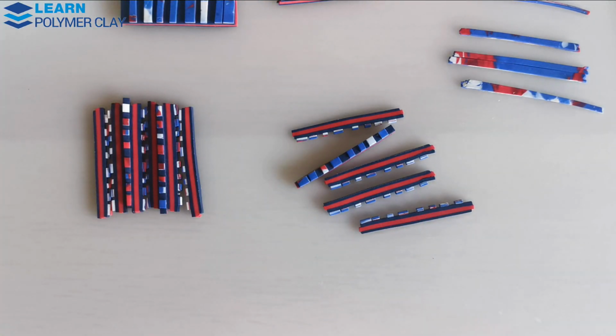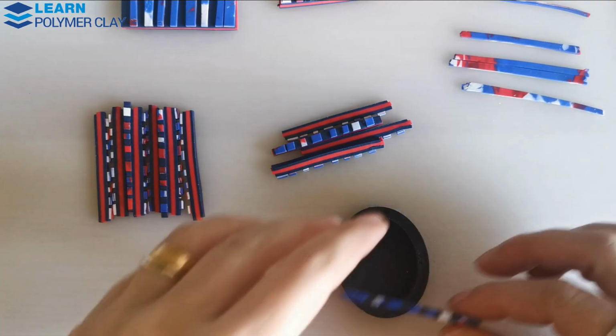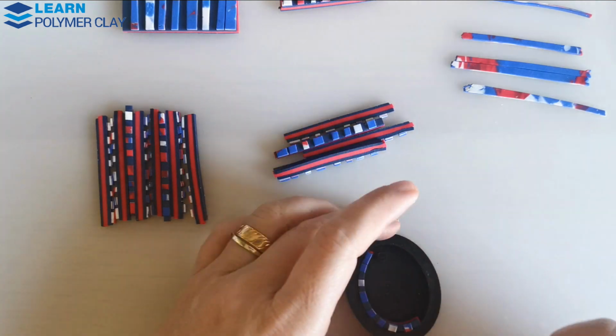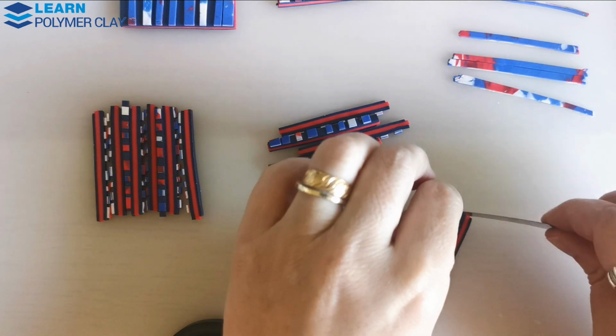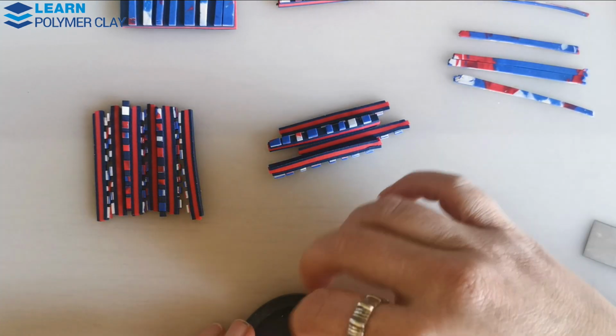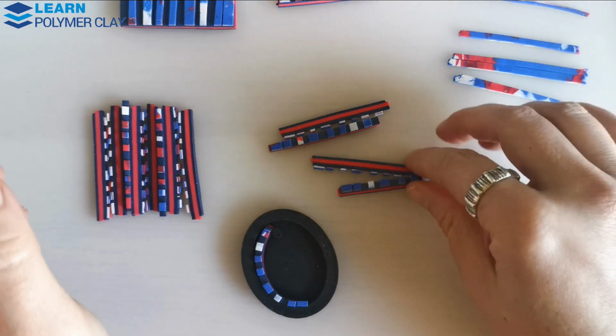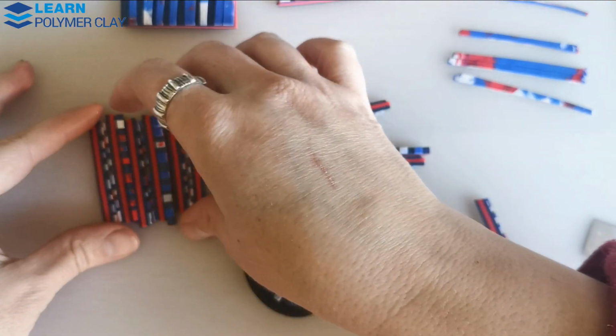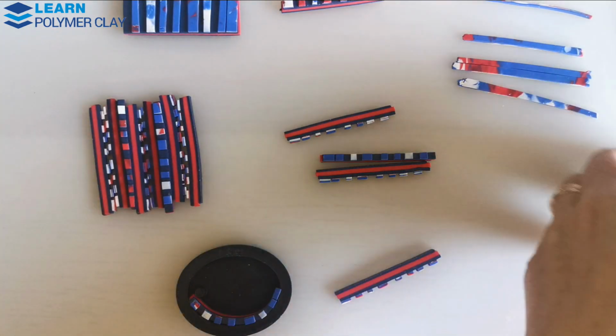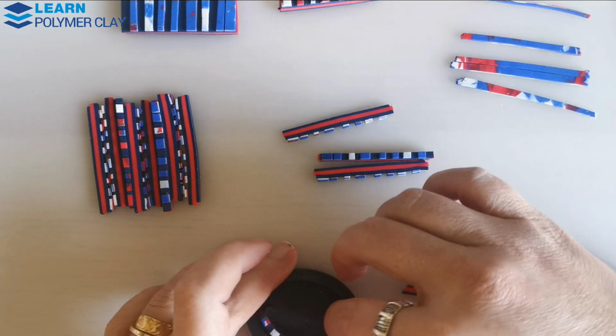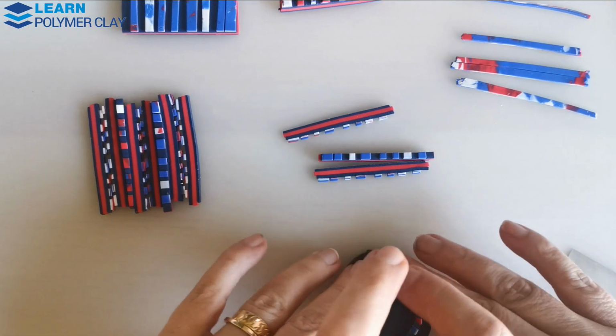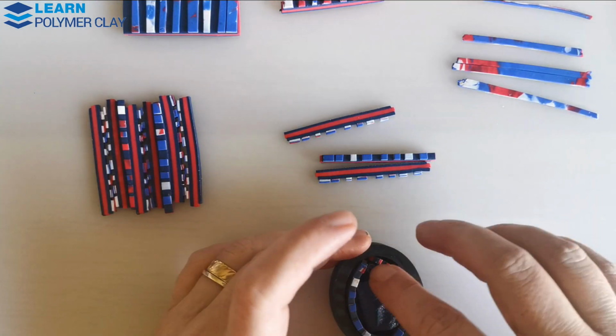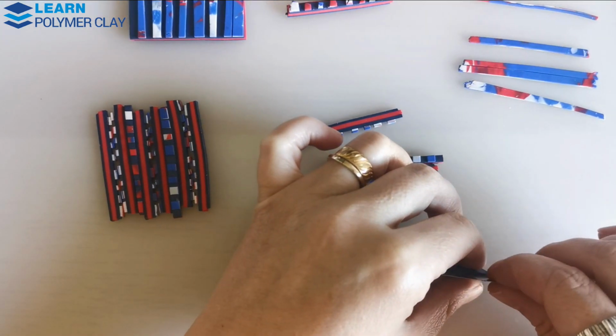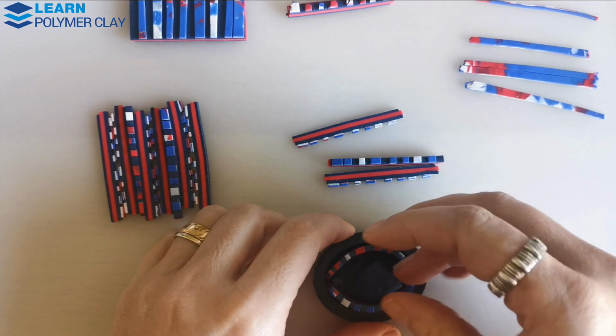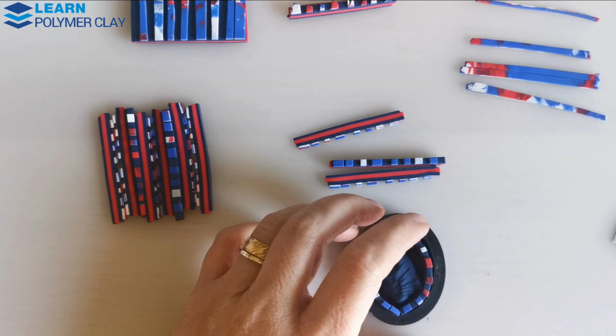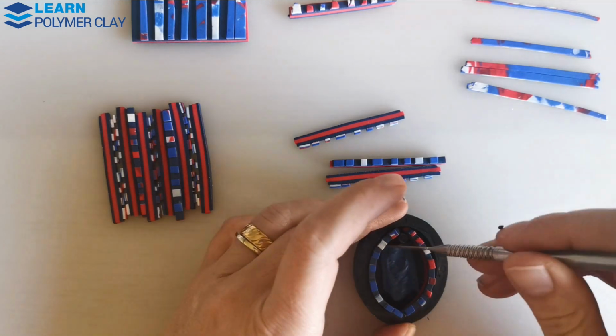And then I decided to use some black silicone molds that I have successfully used with epoxy resin, and that turned out to be not a great fit for UV resin. I think the UV rays would not go through, and my pieces did not cure properly. So if there's a lesson to learn here, is that you should consider using light color silicone molds with UV resin especially. And I wanted to tell you that using such black molds for UV resin was not a good idea, because I wanted you to avoid making such mistakes, and we all learn from each other.